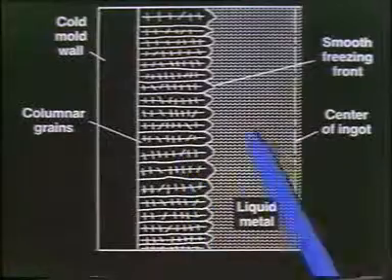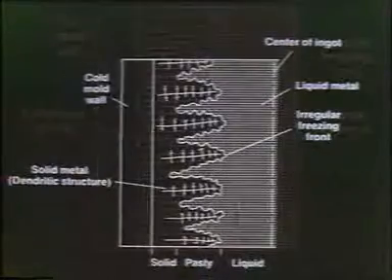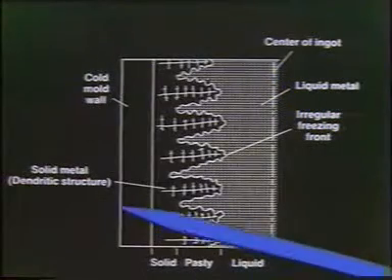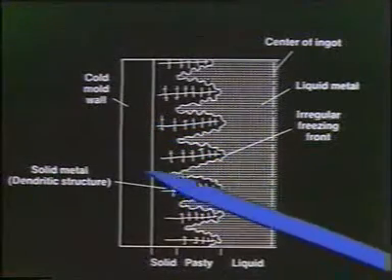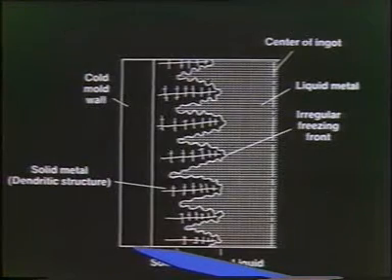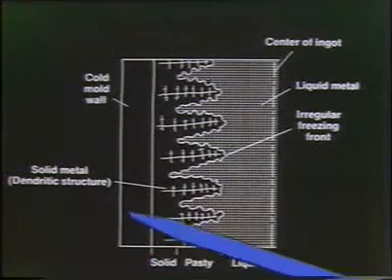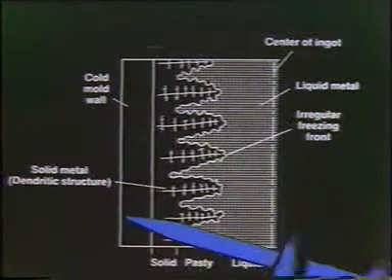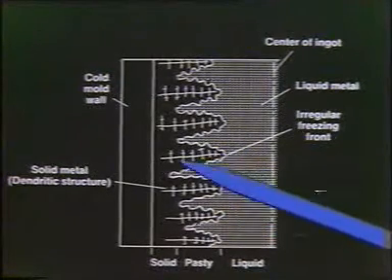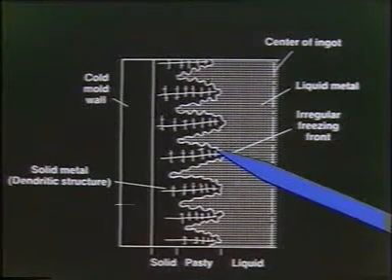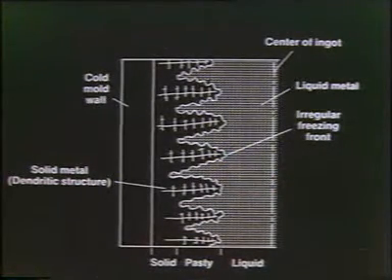If you look at an impure material — an ingot that's solidifying — the dendrite is no longer a perfectly straight thing. It's kind of mismatched and bent over. The reason is that as the material solidifies, it's rejecting an impurity. And as it gives up this impurity, the solid that's growing is now growing into a different alloy composition than before. So in characterizing the materials, we don't have to concern ourselves with just grain size, but with all of these micro situations that will occur in the material.